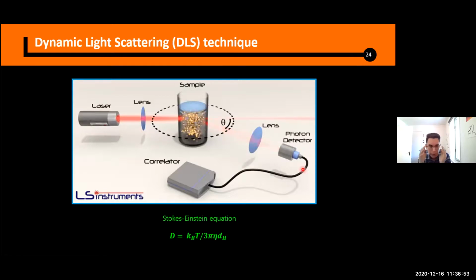With this technique, the sample is illuminated with monochromatic light, such as lasers. The resulting scattered light, or time-dependent scattered light, of the particles, because of the Brownian motion of these particles in the solution, is measured by fast photon detectors. And by analyzing this time-dependent scattered light with a correlator, we can determine the particle size, or the hydrodynamic diameter, of these particles by using the Stokes-Einstein equation.